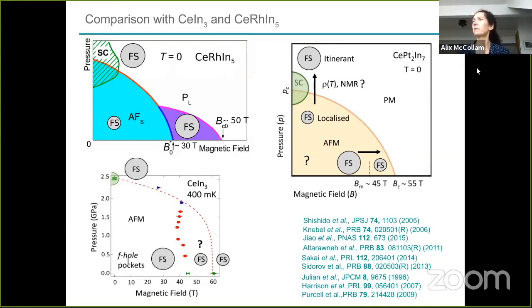There's a question about, does the information on the Fermi surface size come exclusively from dHvA oscillations? Are there problems then due to finite extent of certain phases in applied magnetic field? Yes, at the moment, this information on the size of the Fermi surface is coming from de Haas-van Alphen or Shubnikov-de Haas oscillations. So by actually using the frequency of the quantum oscillations to measure the size of the Fermi surface.